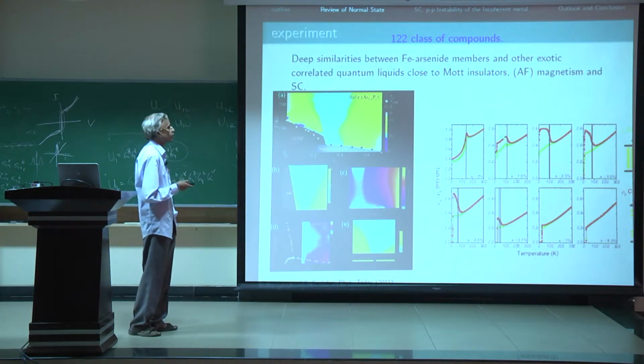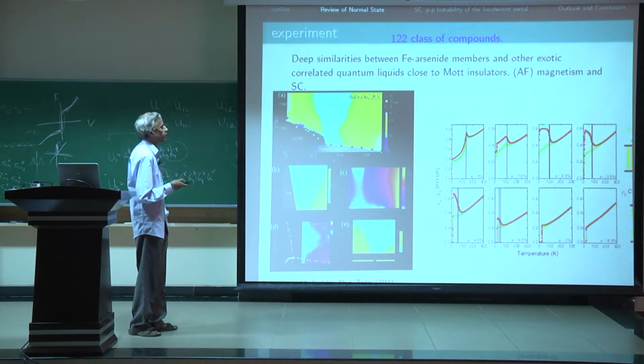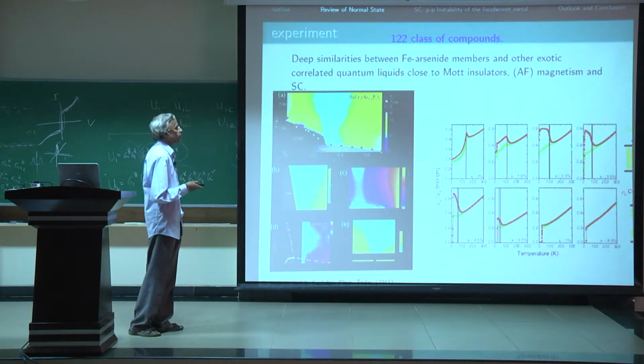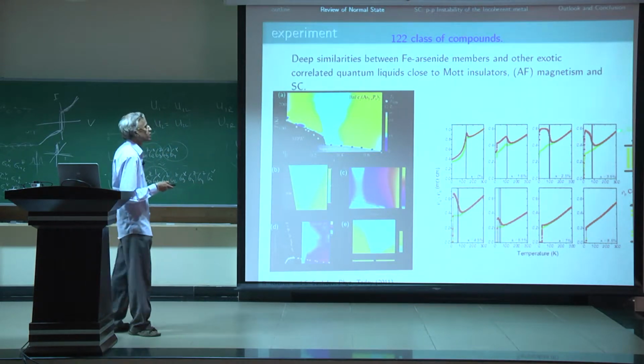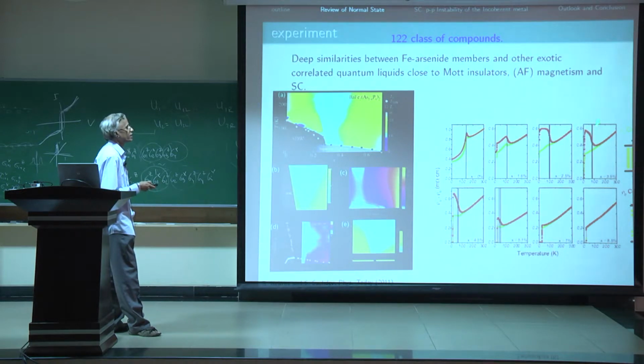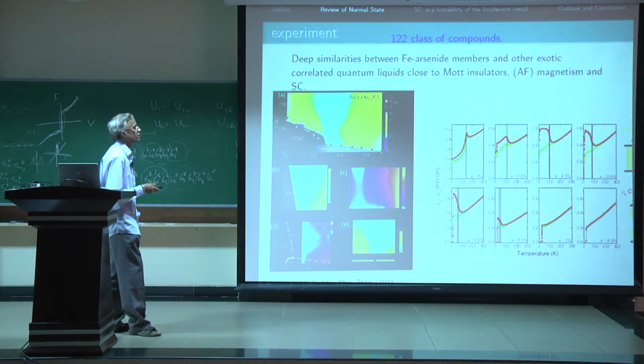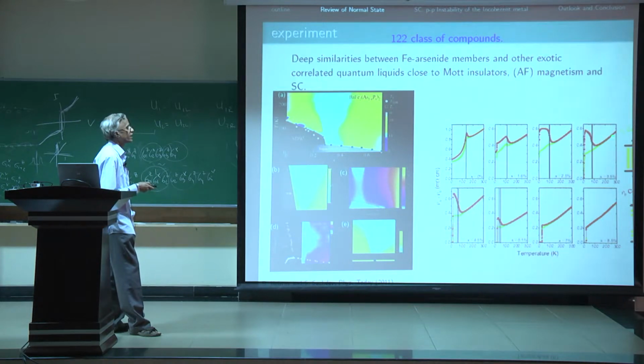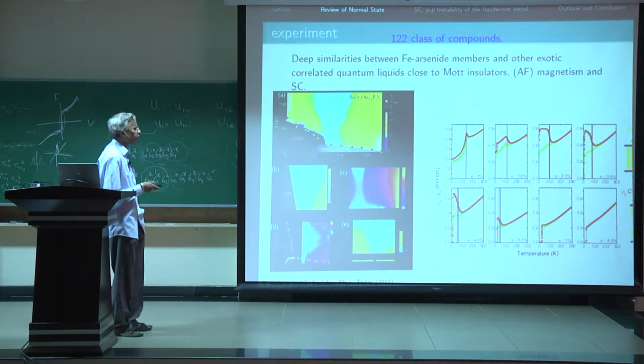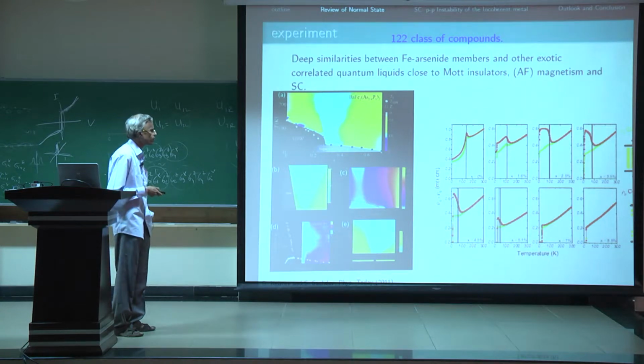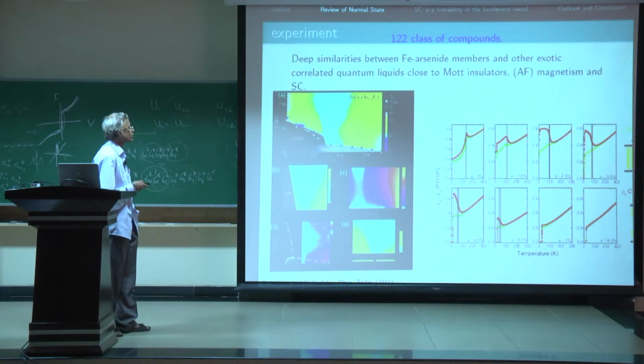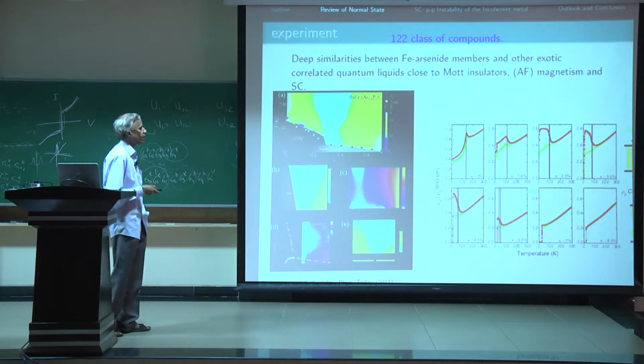Further, the anisotropy also increases, and in particular the B-axis resistivity actually shows insulating-like behavior right up to lowest temperatures, and the transition to superconductivity in the underdoped regime seems to be from an insulator-like state rather than a metal, as far as this direction is concerned. But on the other hand, along the A-axis, you still see very bad metallicity with quasi-linear temperature dependence. What is important to note is that this anisotropy vanishes exactly around or at optimal doping.